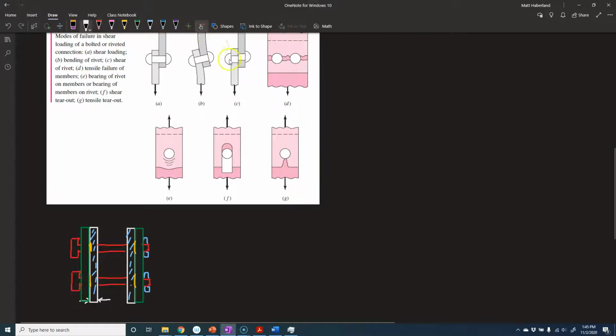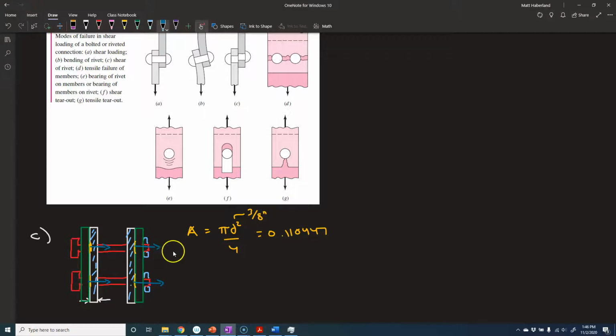So we'll call this C because it's corresponding with this case here. All right, the area of each of these is pi d squared over 4, where d is the major diameter of the bolt, which is 3/8 inch. So that area is 0.110447. Now the shear stress in the bolts, it's going to be a shear stress because the surface normal to these areas is this way and this direction. And the load is coming out of the page towards us. So those are perpendicular. We've got a shear stress that is whatever the force is divided by 4 times this area.